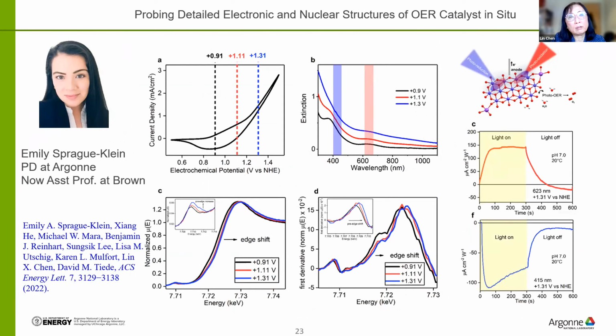Right now we're doing both electro and photocatalysis because it does absorb some photons, but even the absorbance is relatively low. However, we discovered a different light response in the UV. It's mostly LMCT transition in nature, so the electron density shifts from oxygen to cobalt. But at the red light, it is going to create an oxidative reaction and increase the oxidation state of cobalt.